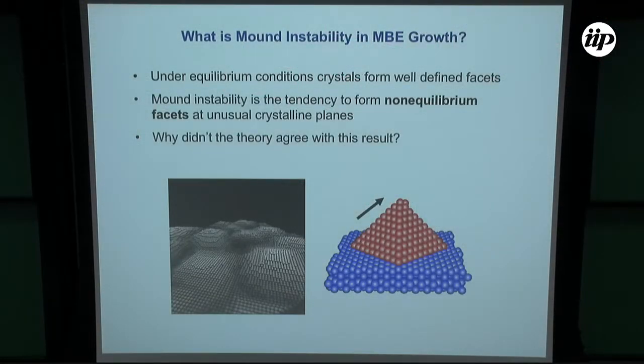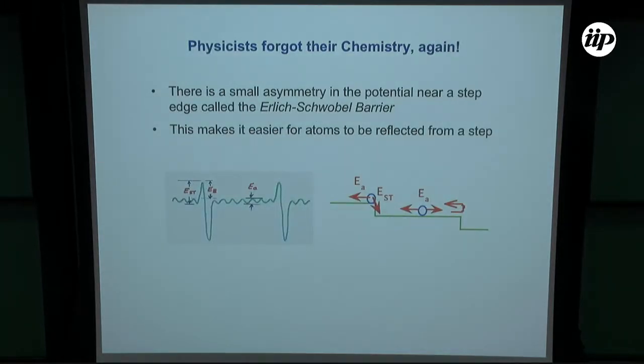And as I will show you from the experimental results, the structure of these facets is very different from equilibrium facets, in the sense that these are 115, 116, 126, or something like that. Nothing that is observed in equilibrium phenomena. So they are unrelated to equilibrium phenomena. All right, to make the story short, it turns out that one thing that none of the theories or simulations included was a tiny effect that had been known for a little while.